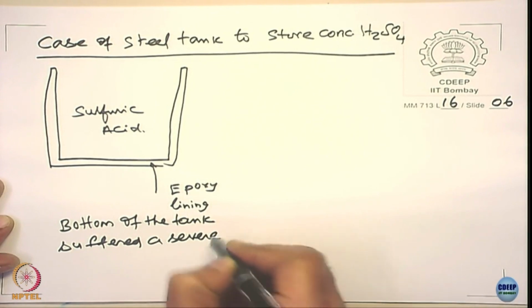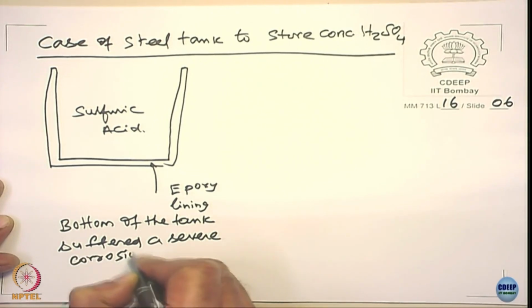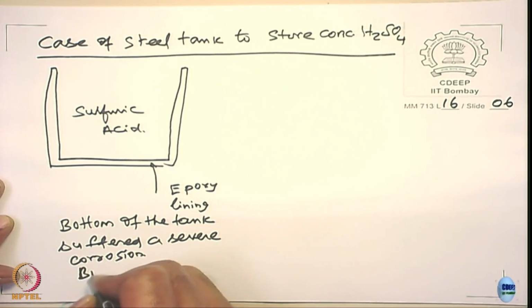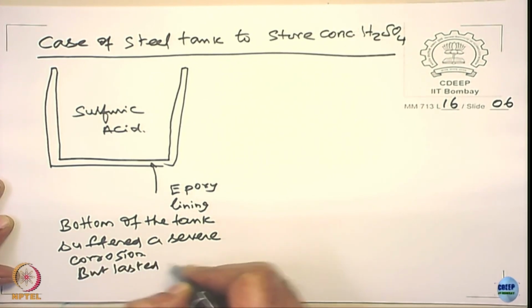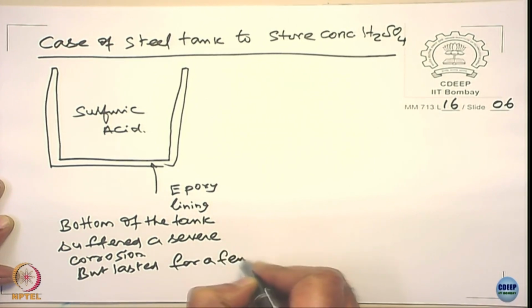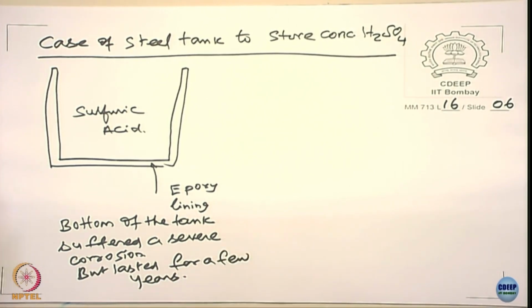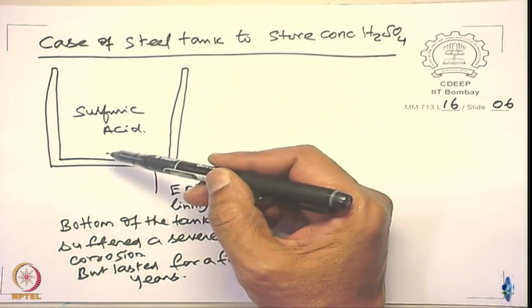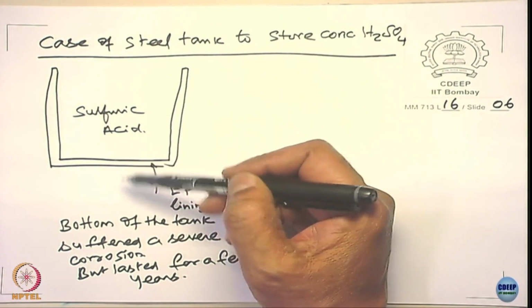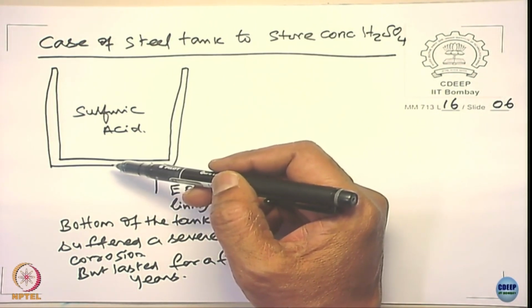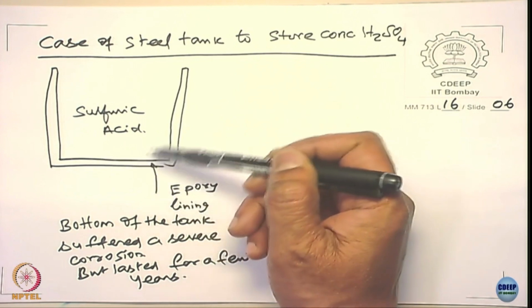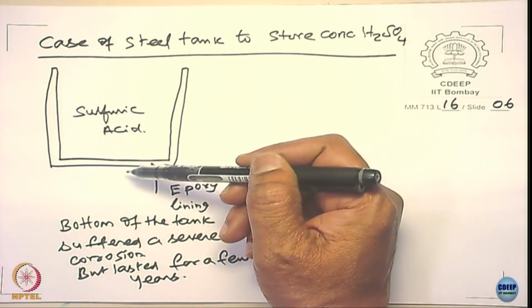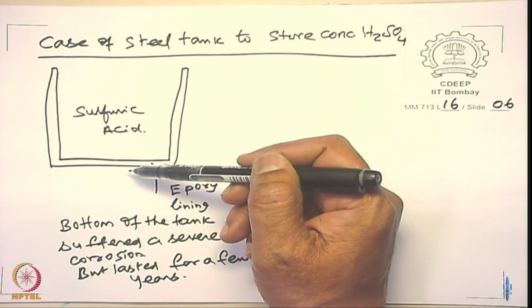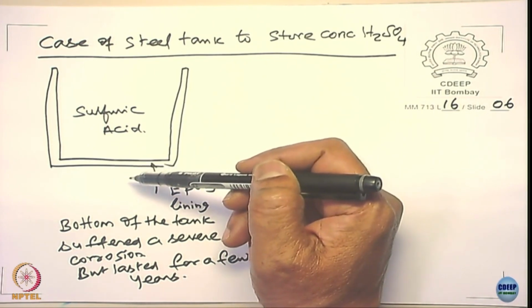severe corrosion, but it lasted for a few years. Seven, 8 years it lasted. And they found that the corrosion is more often on the bottom, and is more due to mechanical damage. They thought that they can line this tank with stainless steel. Stainless steel is harder and mechanically it is quite sound,